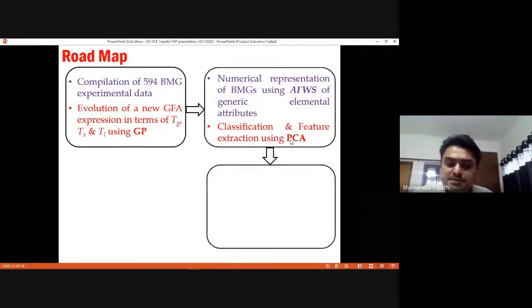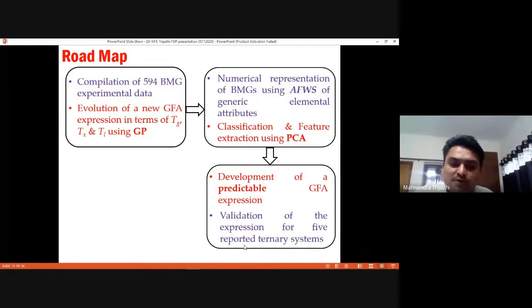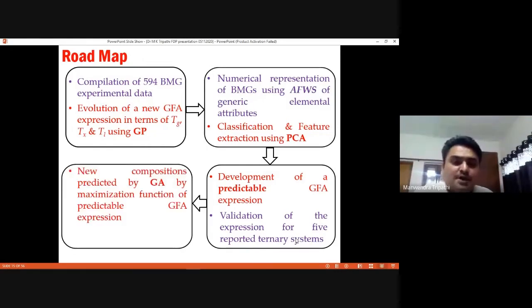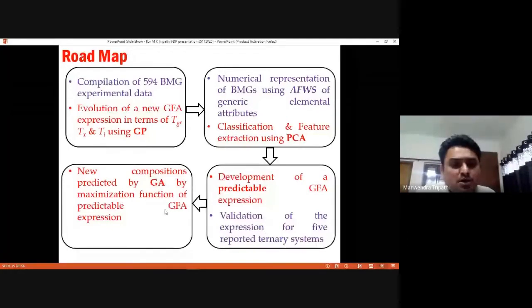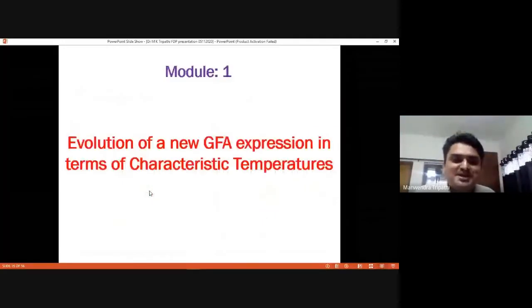And after that, we have developed a predictable GFA expression. And doing that, we have done validation of the expression for 5 reported ternary systems. We have seen that whatever we are predicting, it is working. And we have developed new compositions using genetic algorithm by maximization function of the predictable GFA expression. And after doing that, we have done experimental validation. So in these 4 steps, I will finish it. So rather I should say we'll complete it. Okay, so module 1, the evolution of new GFA expression in terms of characteristic temperature, right?